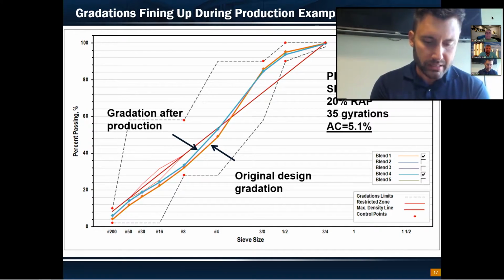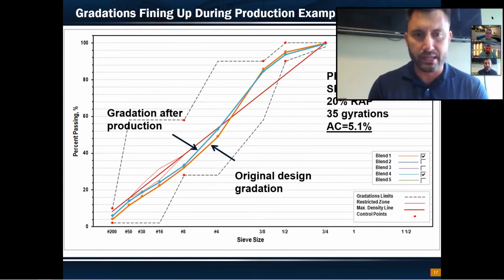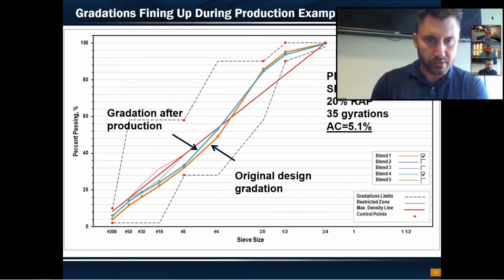The reason is that there's about a 2.5% increase from the reduction in the RAP content, down from 20 to 15%. If you're assuming 5% in your design, typically 20% would be 1% AC. Since we've reduced that to 15%, that means 0.75% AC is coming from the RAP.